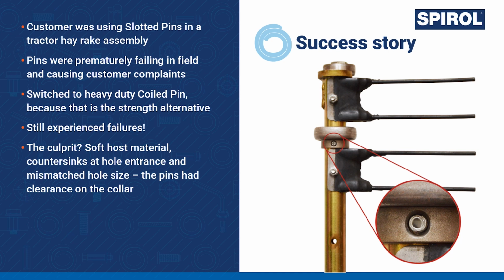This was further compounded by a large countersink on the entrance to the hole, which introduced an additional bending stress on the pin. To solve the problem, rather than going to a stronger pin, the hay rake manufacturer actually needed a more flexible pin. They needed a pin that was strong enough to resist the dynamic forces that occurred during use, but one that was also flexible enough to absorb the shock and vibration to isolate the hole from the force versus simply transmit the forces onto the hole wall. The countersink also needed to be removed.